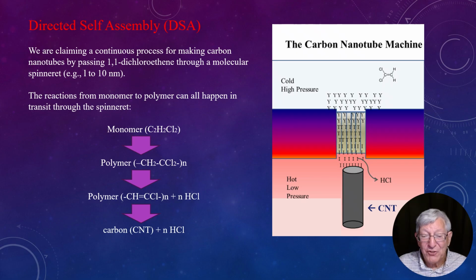I might mention I take some encouragement from the fact that I've noticed that when people are making carbon nanotubes from an iron catalyst, the smaller the iron catalyst particle, the better the carbon nanotubes. Because basically, I think if the iron particles are on the same scale as this 1 to 10 nanometers, then you have a much better chance of getting a single nanotube coming off of there, which is, I think, what we're trying to strive for here.